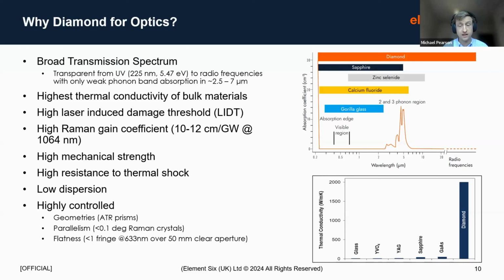In the case of diamond, its very high thermal conductivity in the diamond substrate means that it can spread the heat from any absorption in your optical coating, and that reduces the peak temperatures achieved in your optical coating, which in turn can lead to things like improved LIDT for your optics. So it really comes into its own for high power optical applications.